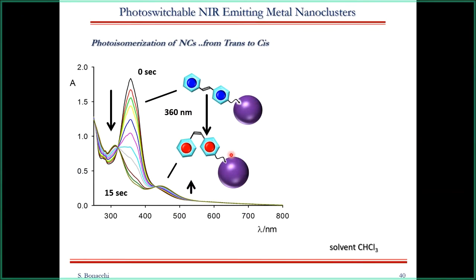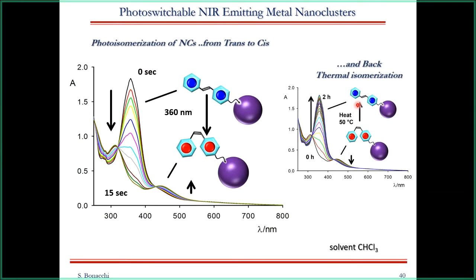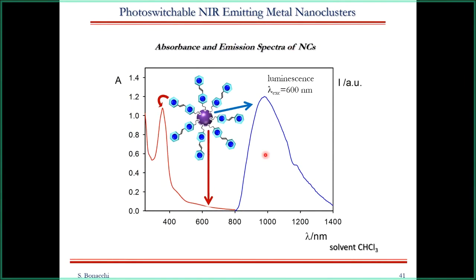And then we proved that even if the azobenzene moiety is anchored on the nanocluster, it's still possible to photoswitch the azobenzene moiety from the trans to the cis, and then thermally back to the trans original form. So if there is this cluster, the activity of the azobenzene molecule is still present, and we can photoswitch this unit several times. And as soon as we look at the emission properties of the cluster, we again observe very nice near-infrared emission, for instance here if we excite at 600 nanometers.